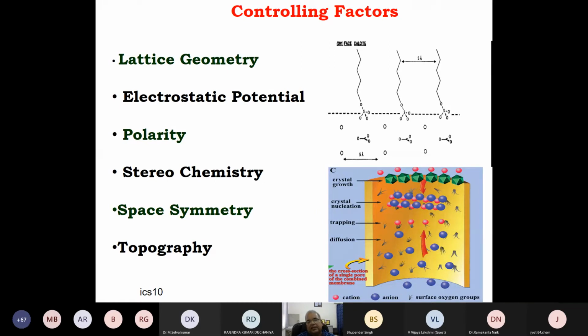But one thing is clear, there is an organic matrix and there is an inorganic phase which is growing in it. If it has grown on the organic matrix, then you have an organic-inorganic interface. Now, control on the inorganic interface or on the inorganic product is possible only if there is a matching in the lattice geometry of the inorganic phase that is nucleated and the spacing available with the supramolecular matrix. There should be a lattice geometry matching.